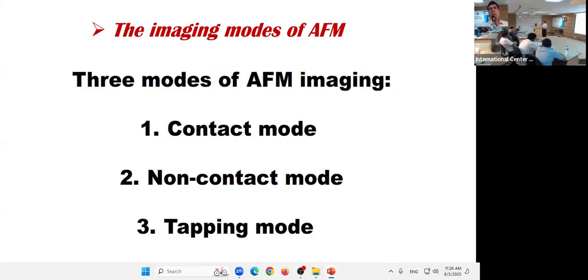The non-contact mode is mainly used for biological samples, where you want their native conformation to remain intact. So you use the non-contact mode because it would not touch the sample. It would just establish a certain distance where it can deflect and generate an image. In between the non-contact and the contact is the tapping mode, which just gently taps the surface. So here the resolution becomes better.